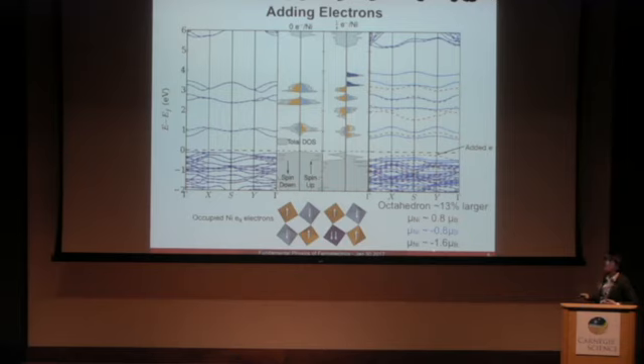If we look at the associated density of states with this nickel, we see now there are only 2 unoccupied eg states, and there is this state that has moved from the conduction band below the Fermi energy. So the remaining density of states stays roughly the same. The slight splitting is due to the fact that we've broken some symmetries. But our overall gap hasn't changed. However, we can see the number of states in this conduction band has reduced in this intermediate doping state.